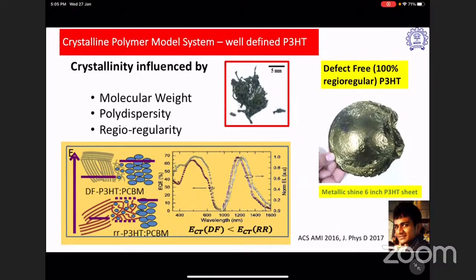With the dotted lines of the energy levels, that shows that it has a more blue-shifted EL. So you get a slight enhancement in the VOC, but overall the photocurrent is more when things are much more aligned. So there's a role of regioregularity: the charge transfer state of the defect-free is lower than the charge transfer state of the regioregular system, and defect-free is the one shown in the hand of Anil Kumar.